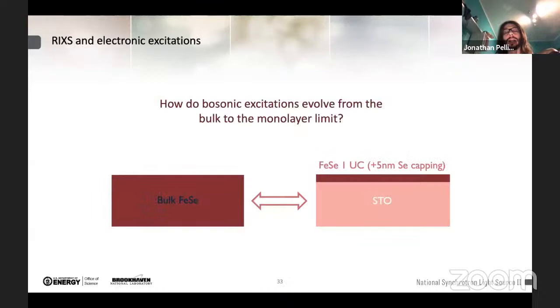So in our investigation, essentially we studied how the bosonic degrees of freedom, which are the ones that RIXS is sensitive to, evolve from the bulk case of iron selenide to the case of iron selenide grown one unit cell thick on STO. On top of this, we had to place 5 nanometers of selenium capping layer in order to avoid any oxidation and degradation of the sample, because these samples are unfortunately known to be pretty susceptible to air degradation.